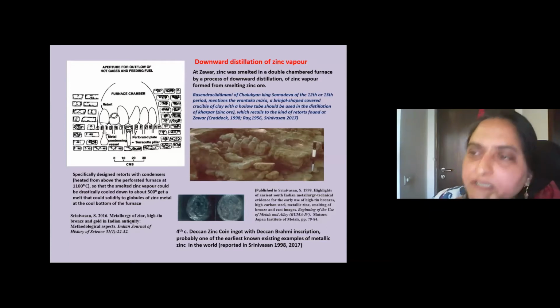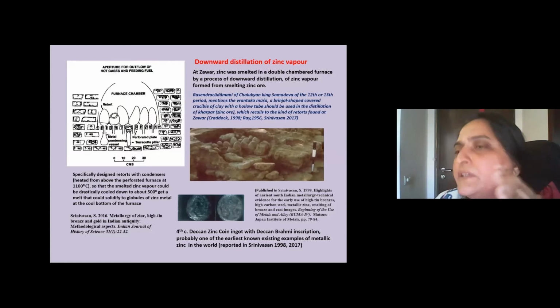Of course, some of these terms, as in Sanskrit, it often happens, are used sometimes quite variably. So one does need to actually understand the context before the translation is done. Karpur is, of course, used to refer to camphor, but in this case, it refers to the zinc ore. And so you can see here, it recalls the kind of retorts that you find in Zawar. And so it's a radical cooling from about 1100 degrees centigrade or so down to about 500 degrees. And then it solidifies to form these globules of zinc metal.